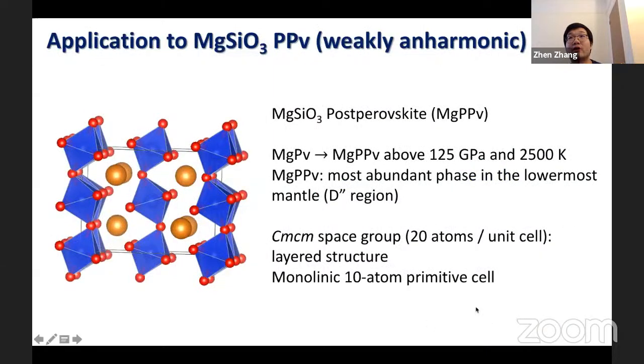We further applied the phonon quasiparticle method to magnesium silicate post-perovskite. Magnesium silicate perovskite is believed to undergo a structural phase transition to post-perovskite above 125 gigapascal and 2,500 Kelvin. Therefore, magnesium post-perovskite is the most abundant phase in the lowermost mantle, also known as the D double prime region. It has the CmCm space group with a 20-atom unit cell. The structure of magnesium post-perovskite is an anisotropic layered structure, so it can be further simplified to a monoclinic primitive cell with 10 atoms.